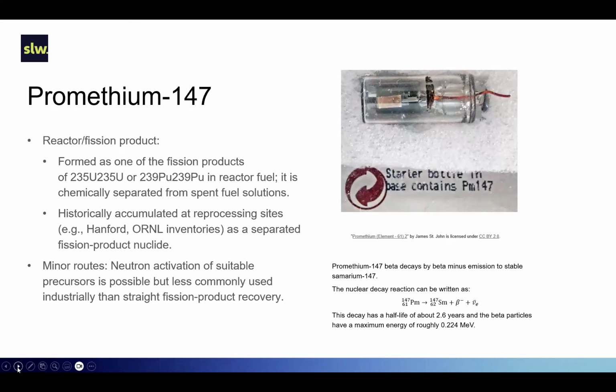Promethium-147 is formed as one of the fission products of uranium-235 or plutonium-239 in reactor fuel. It's historically accumulated at processing sites such as the Hanford site, and minor routes, neutron activation of suitable precursors, is possible, but less commonly used industrially than straight fission product recovery.